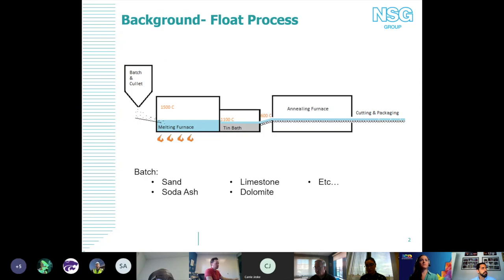So just a little background in how this works. Essentially, we have our float process to create the glass. We have our raw materials go into a melting furnace at 1500 C. Essentially, all the bubbles are pulled out. This molten glass gets poured onto a molten tin bath and is floated over that to give it the flat properties that you see. And it is pulled to whatever thickness the glass is being designed to be. Afterwards, it comes out of the tin bath, goes into the annealing furnace to help relieve any residual stress that may be within the glass, and then it is cut and packed. So that's just a general layout of how glass is made.